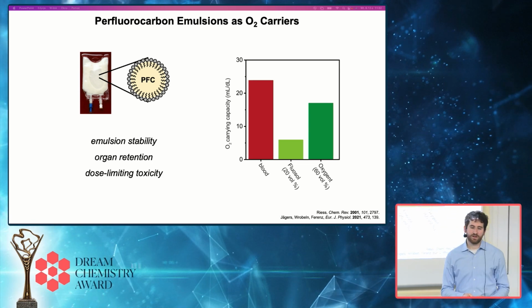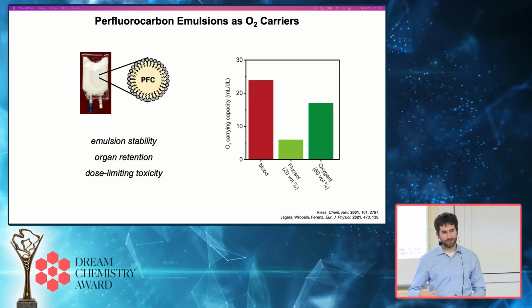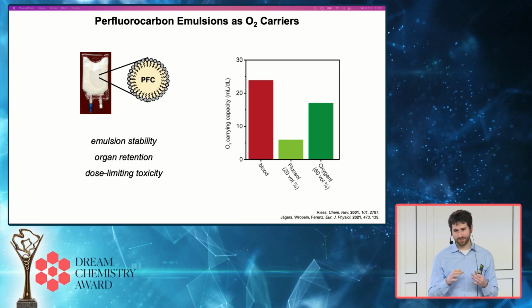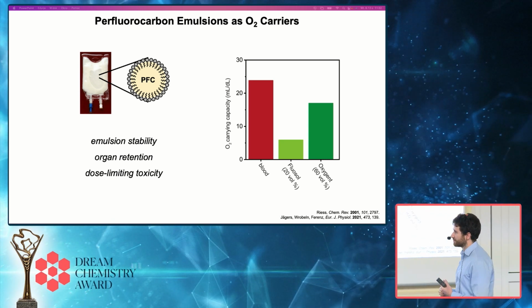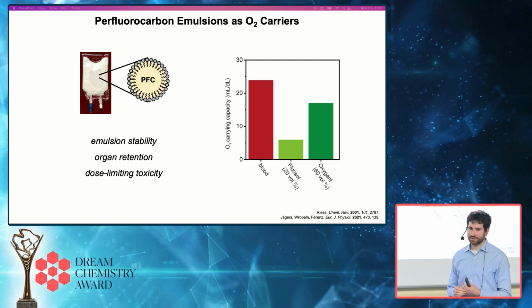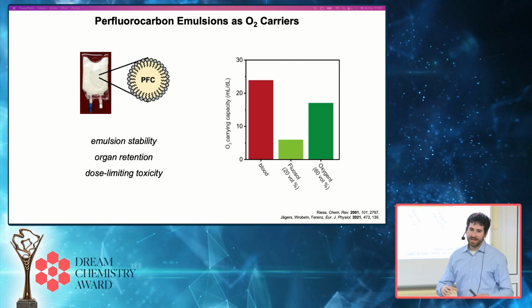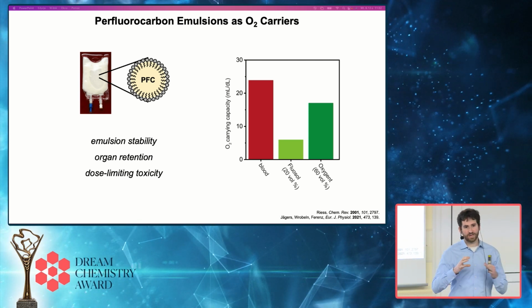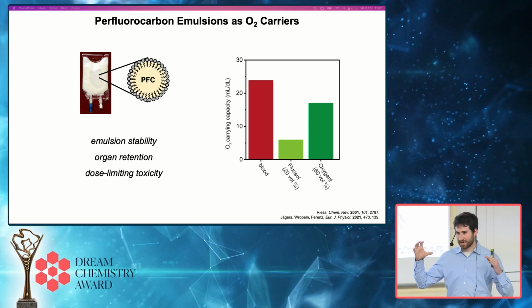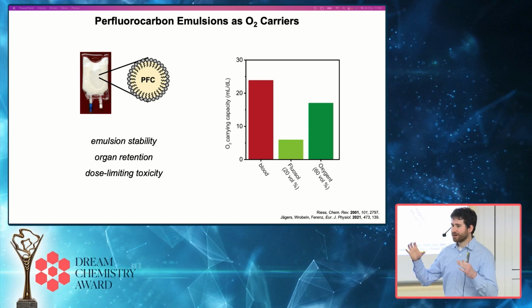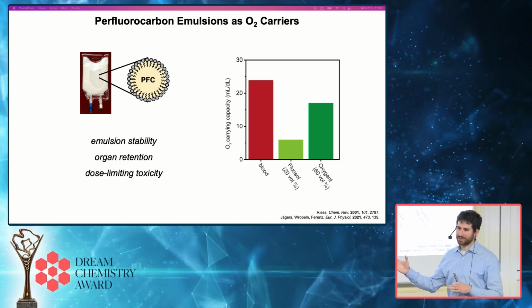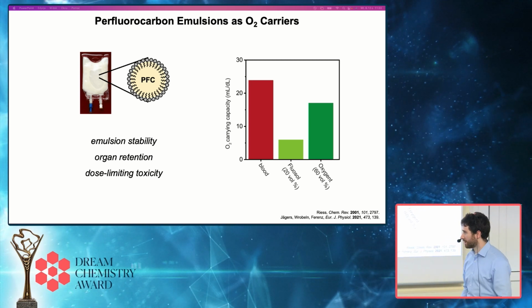The other issue with these emulsions is that perfluorocarbon molecules are really good at dissolving oxygen because they're very weakly associated, but that causes a lot of issues for the stability, particularly long-term stability, of these emulsions. So droplets of perfluorocarbons tend to coalesce and grow larger in size over time, and that creates challenges as you get to larger and larger droplets, particularly if you want to do anything that involves injecting them into the body.